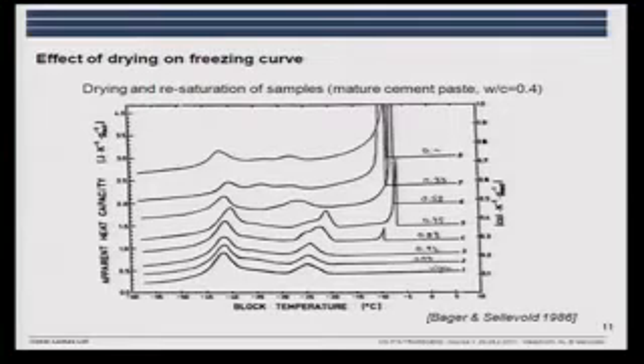How it's described now is that when you start, the freezing front will start from the outside and move inwards. So if you have very fine pores on the outside, the freezing front has to penetrate these. It will take some time. And then behind it could be that you have larger pores. So the freezing curve is a picture of the bottlenecks or the threshold pore sizes. Similar to what we see for mercury intrusion, we have to press the mercury in, and the first pore size where we have ingress, that would be the threshold, the bottleneck. For instance, if I have to freeze from here, I have to go through this small one before I can enter the larger one behind. Threshold pore sizes. So this is what we see.